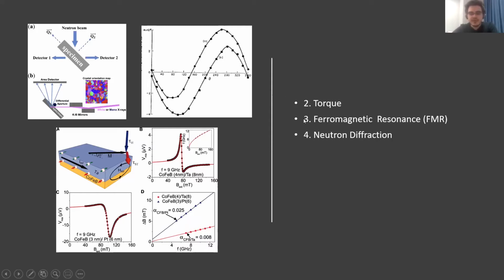Ferromagnetic resonance, which Ege will talk about in the following week, is also a technique to measure exchange bias characteristics of our system. In FMR, samples mounted in a microwave cavity are subjected to a high frequency magnetic field with a DC field inside. By sweeping the frequency of the applied AC field, we observe the resonance frequency of the spin waves, and from it we can derive the stiffness of our material, so we can see the exchange bias characteristics.